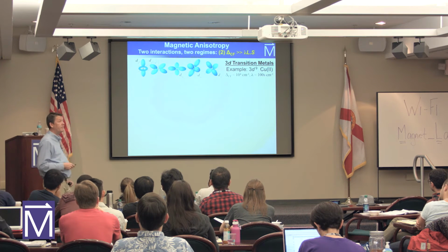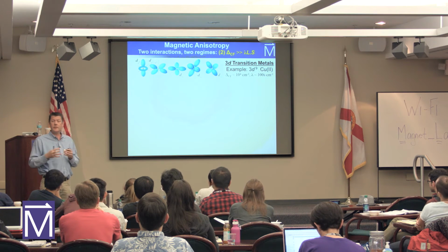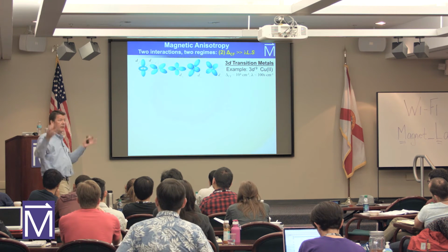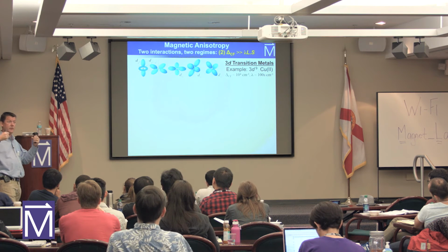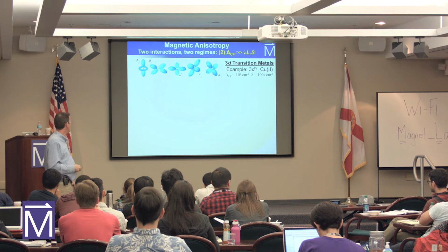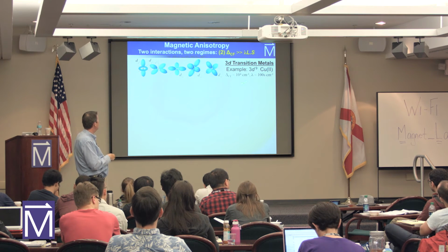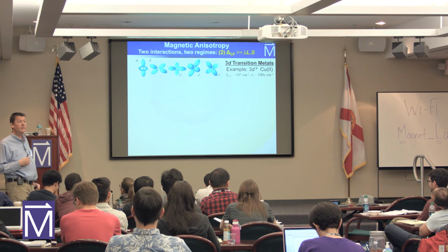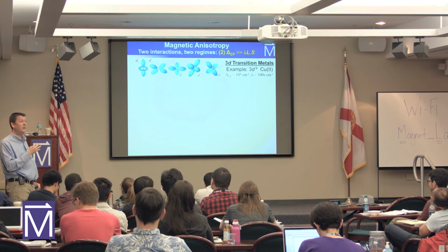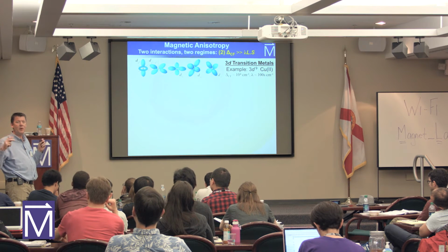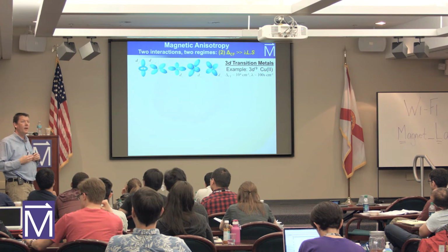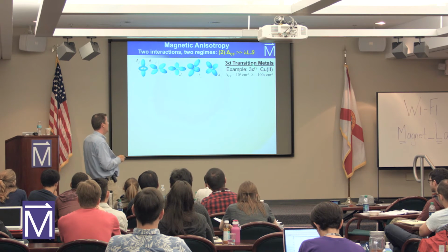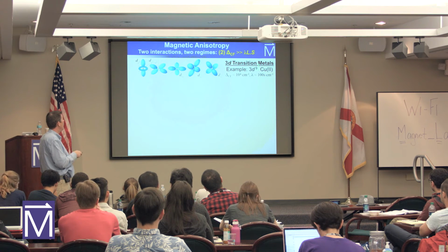you have the opposite. In transition metals, the d electrons are actually responsible for the bonding. So they interact very strongly with the surrounding atoms which form the chemical bonds. And so in this case, it's completely back to front. You have crystal field energies now that are often thousands of wave numbers. And the electrostatic picture that I've shown you up to now is a bit of an oversimplification, because you have to worry about covalency and so on, and a lot of quantum mechanical corrections. But still, you get crystal field energies that are often thousands of wave numbers.